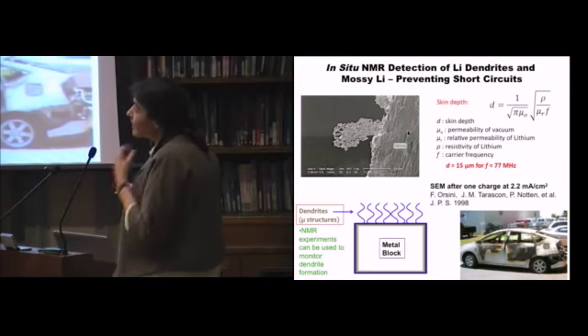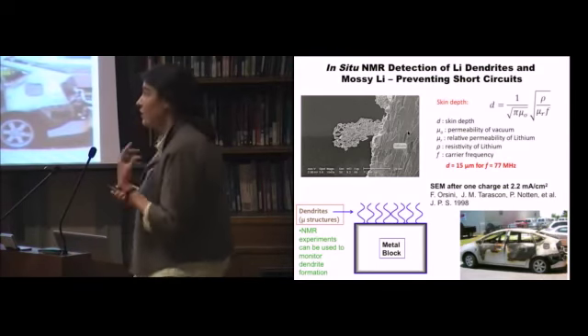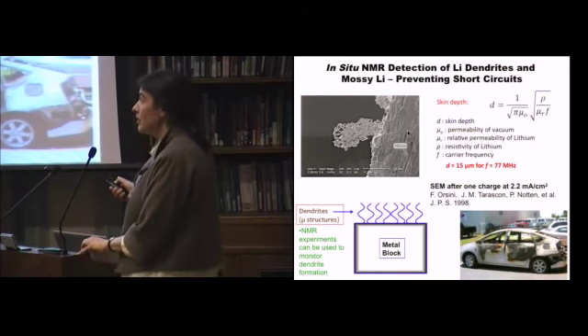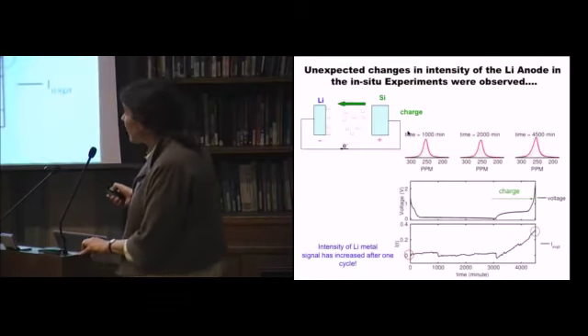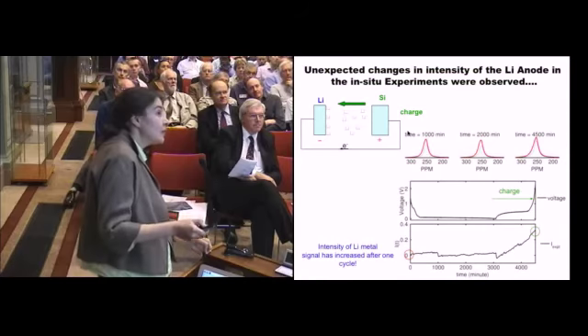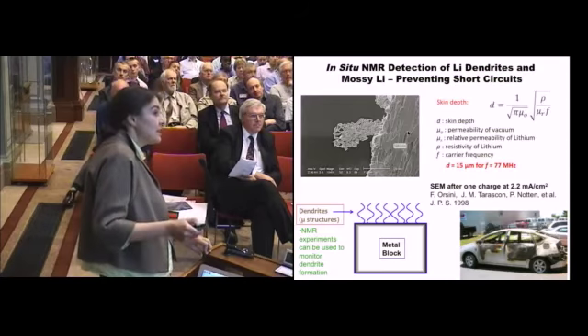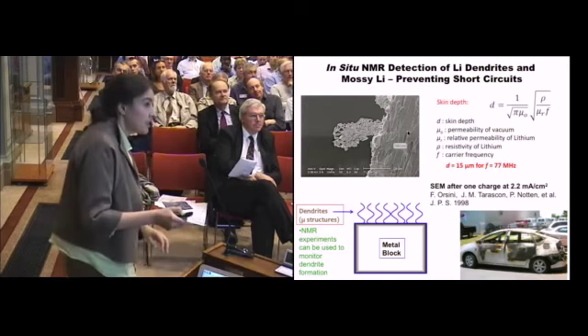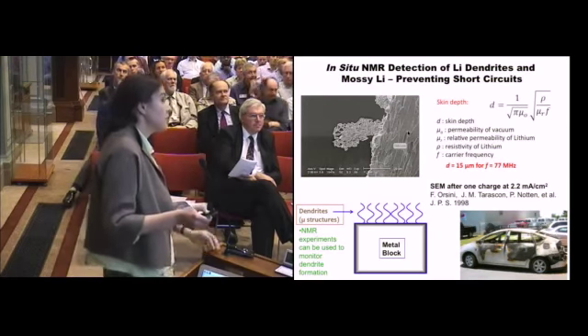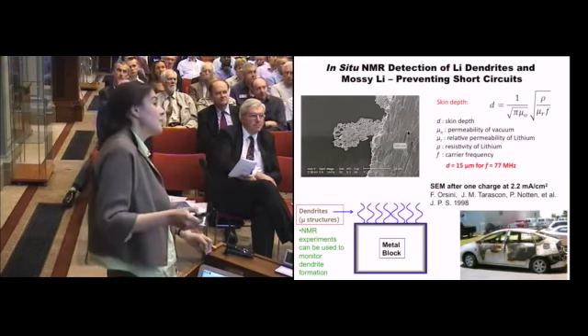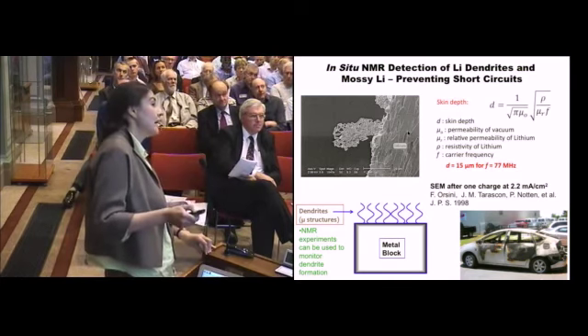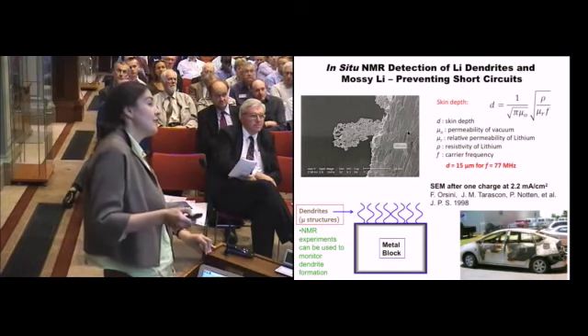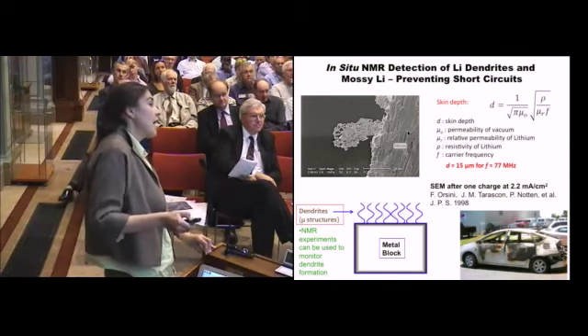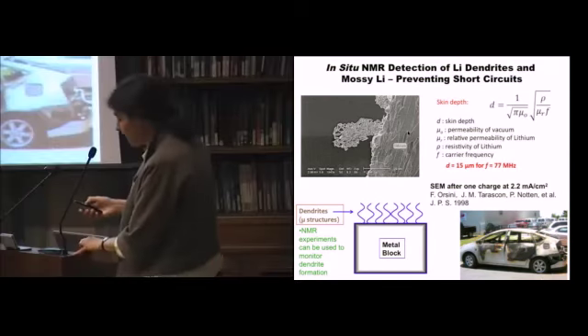What's going on actually is I'm forming a dendrite. So it's these dendrites I talked about in the beginning of my talk. As I go back here and I return the lithium onto the lithium anode, it's forming these dendritic structures. It turns out that I can't get the radio frequency pulses that I use to do NMR through a block of lithium. I can only get through the first about 15 microns. So I have a way of seeing these dendrites and separating them from the lithium metal.